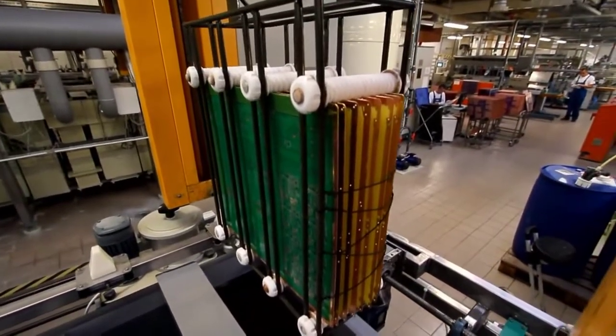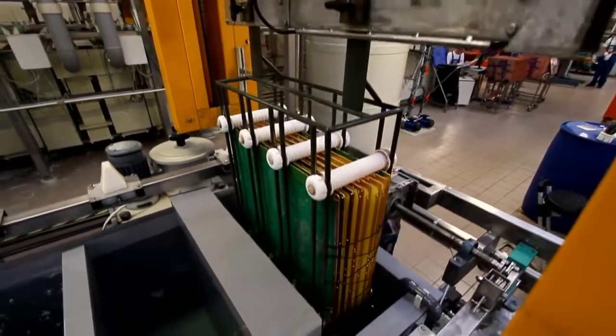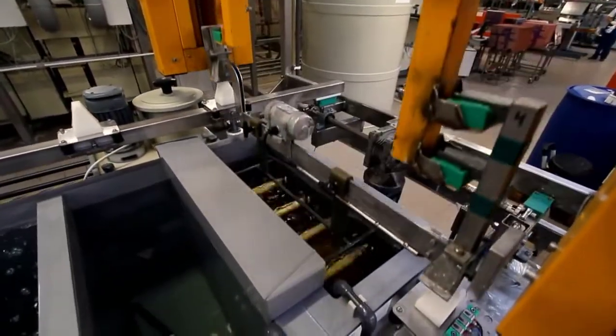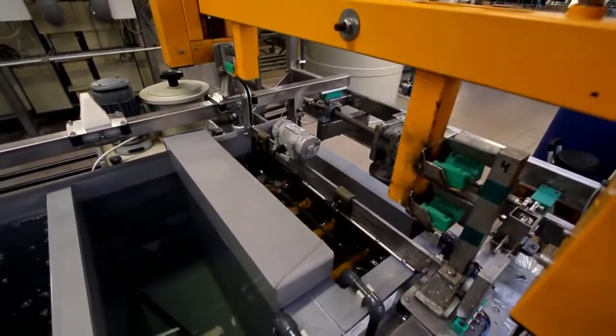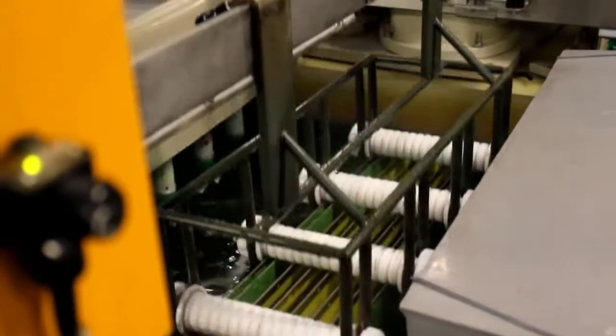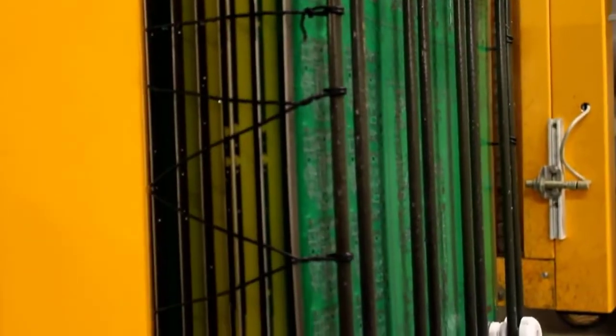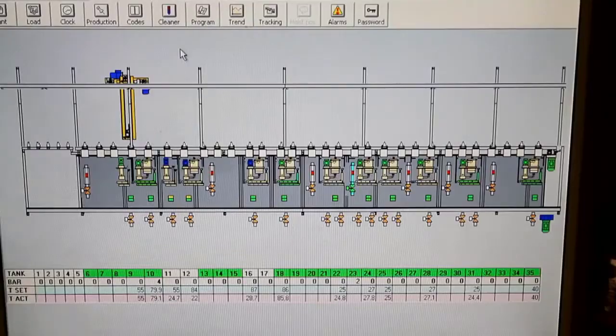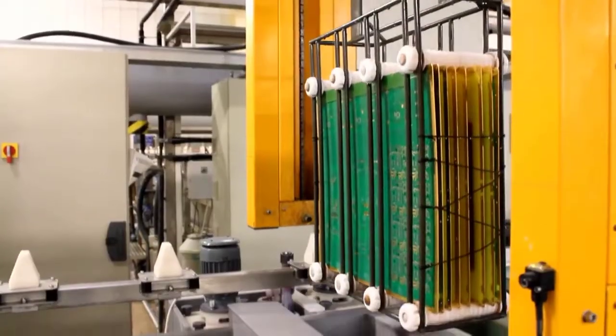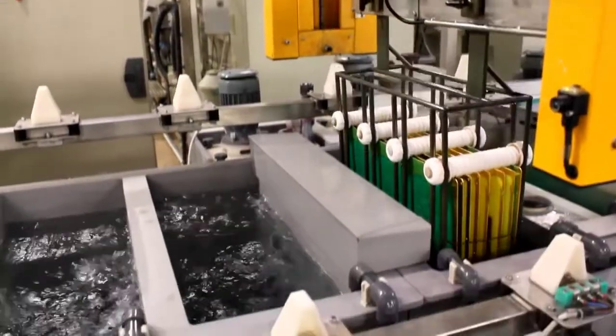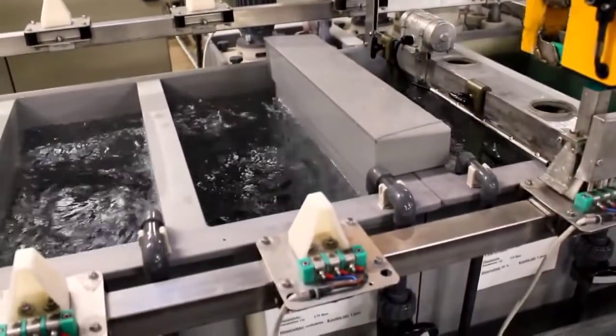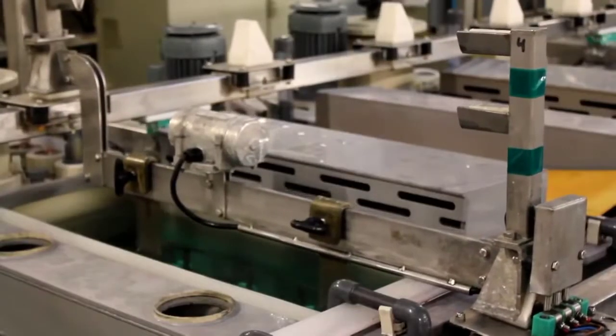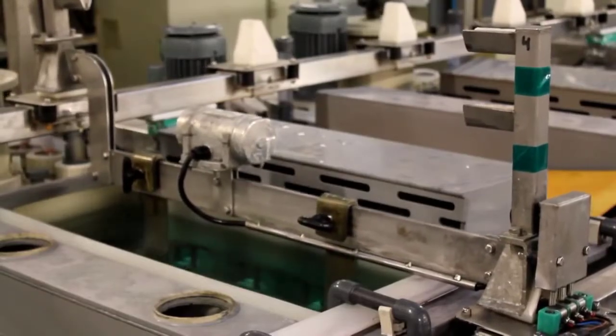Under the EU Restriction of Hazardous Substances, or RoHS, legislation, we cannot use lead in our finishes. So we offer gold over nickel, as you can see. Chemical silver, using a similar process to deposit a sterling silver finish, or lead-free hot air levelling. For this, the panel is lowered into a bath of molten tin. As it is lifted from the bath, hot air jets blast the surplus molten metal from the panel to leave an overall coating of tin about 2 microns thick.